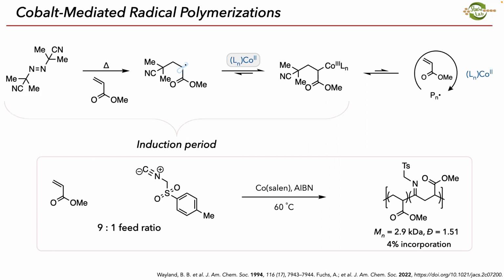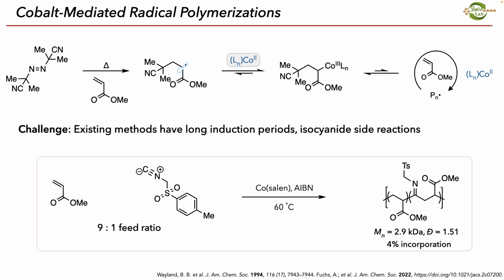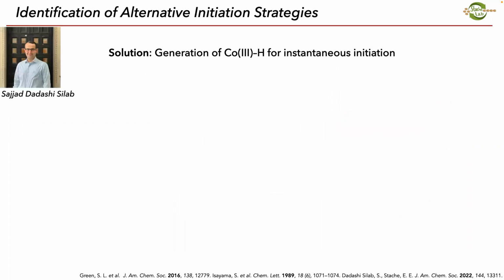And so the challenge here is that we have a very long induction period. That means there's no polymer growing, but we have radicals which are starting to be generated. And so we first need to generate a high enough radical concentration that we push the equilibrium over to this dormant species. So then we get into the polymerization through this reversible deactivation equilibrium. And so right now we have too long of an induction period so that side reactions can occur with our isocyanide. And so we needed to develop a new strategy for initiating these types of cobalt-mediated radical polymerizations.